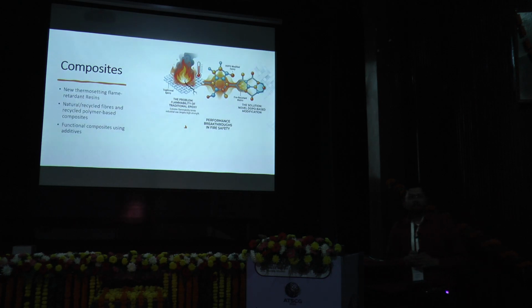Then in composites, because I am from a textile chemistry background, I thought why not use textile chemistry concepts of conventional processing in composites. So I found in composites resin is used. Everybody is using epoxy, right? And it is not flame retardant. So what I thought was, can I tweak epoxy resin? So we have synthesized a new epoxy resin which is flame retardant. So you have to just put it along with the composite material, you will get inherent flame retardancy.